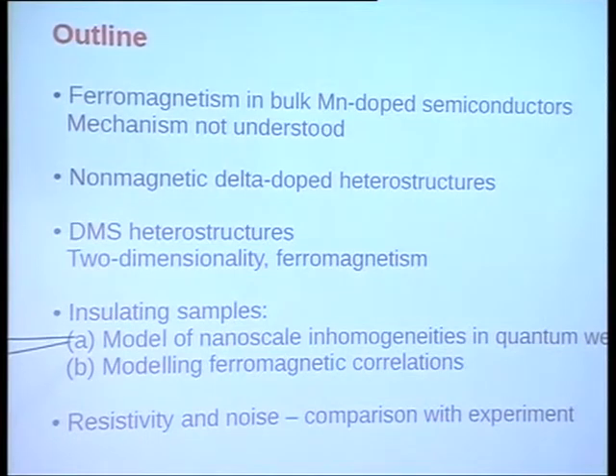In the insulating samples at low carrier density, we have phase separation, and we have a model describing how these inhomogeneities come about as a competition of disorder and nonlinear screening. And finally, we model the ferromagnetic correlations into this, decided by Coulomb interactions largely, and discuss resistivity and noise in this context and compare them with experiment.